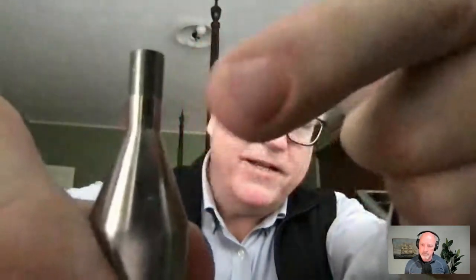In this case, in a demo tube, it has the micro pattern on the inside and the outside. On the inside, we put the micro pattern on the mandrel. And again, I'll hold up for those watching, you see some small lines on the end here. And on the outside of the tube, it's put on the inside of the outer die.